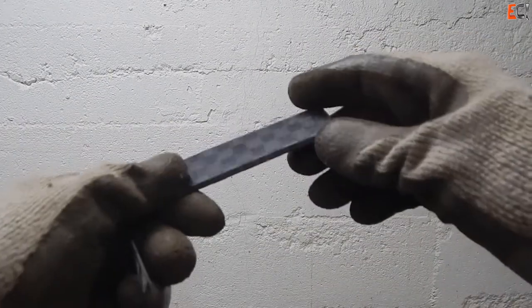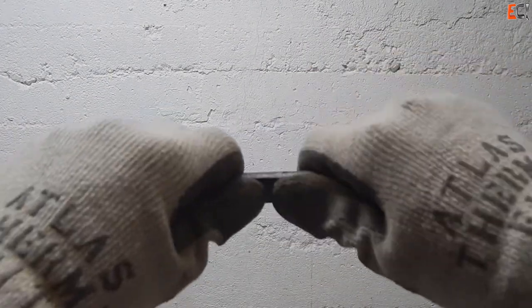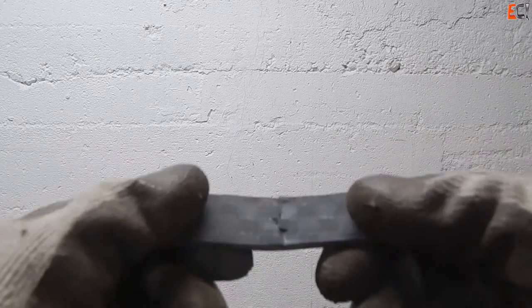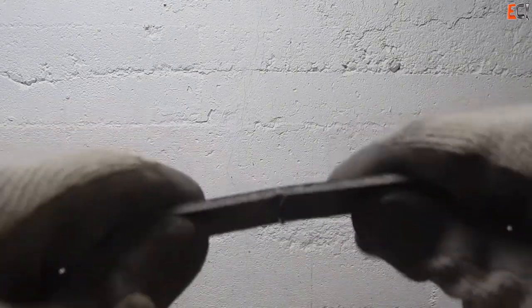And breaking a little piece, see it fails the bottom skin in compression. And it fails right along the weave where there's that little bit of crimp and the fibers are not straight.